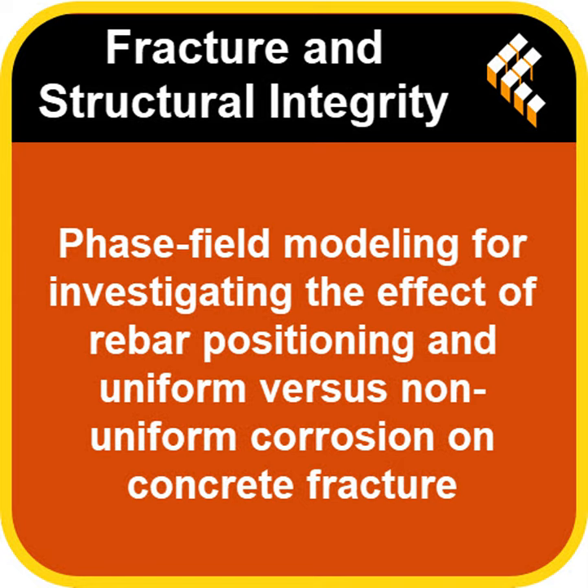What else? Second, even with symmetrical layouts, where that symmetry is corners versus edges, leads to distinct cracking behaviors. And again, non-uniform corrosion often makes those differences clearer. Point 2. Symmetry type matters too. And 3. Third, concrete cover thickness is absolutely crucial. No surprise there, but this reinforces it. Thicker cover consistently requires more rust accumulation to cause cracking. It buys you time, increases resilience. More cover is good.